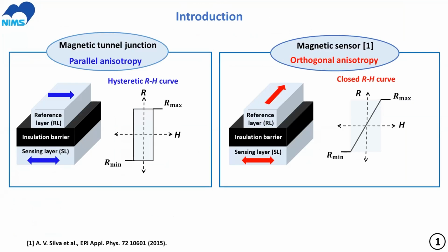Okay, so the magnetic tunnel junction is a magnetic element consisting of two ferromagnetic layers, as you can see here. One is the reference layer, the second is the sensing or free layer, separated by an insulation or oxide layer. When the magnetization configuration is parallel, you will have a very low resistance, we call R minimum, and when the directions of magnetization of these two magnetic layers are anti-parallel, you have a high resistance, we call R maximum.